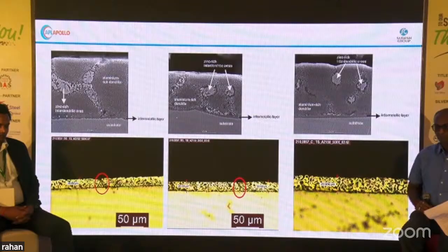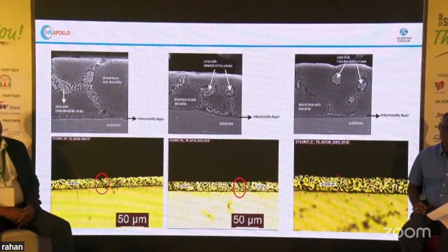On the bottom left side, you can see that at a low cooling rate there is a straight path touching the intermetallic compound. So very easily, whatever corrosion is taking place touches the intermetallic layer, which is the main protective layer. On the right side, when we increase the cooling rate, the spangle size decreases and there are so many zigzag passages. So it will not easily touch the base metal.